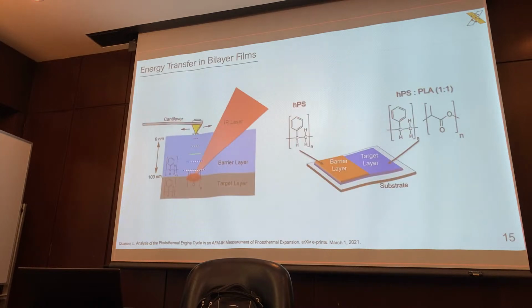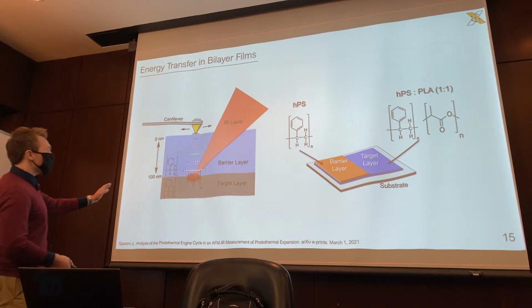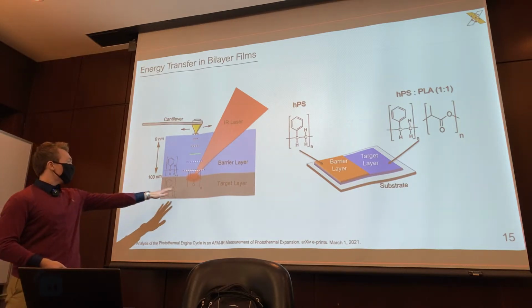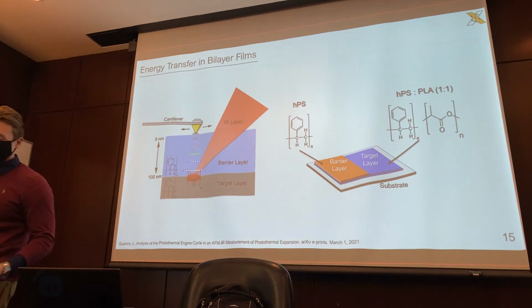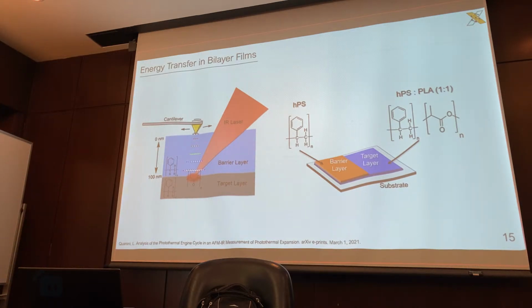So with that in mind, I wanted to look at energy transfer in some of these bilayer films, because the more interfaces you have, in some cases, you will have a greater loss of energy. And there are many different ways you can lose energy. Between the interfaces of the material, as we see here, a few weeks back we created some bilayer samples which were stacked vertically, where we created a barrier layer of polystyrene, and then for our target layer, it was a blend of PLA and polystyrene. And the purpose of this was to create a very well-defined structure that we might be able to see underneath this barrier layer.